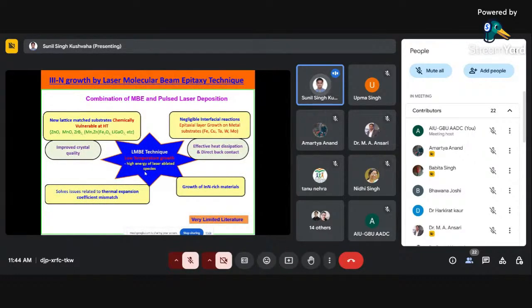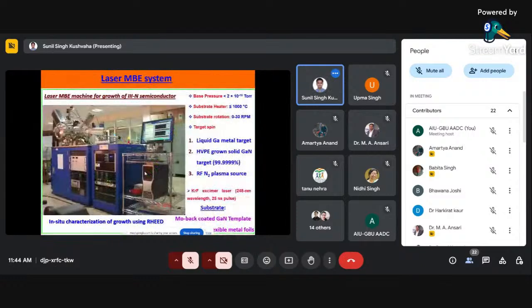So basically, at NPL we have this laser MBE technique, and that is one of the techniques especially used when we are talking about vacuum. This is what we call an ultra high vacuum system. The base pressure is 2 times 10 to the minus 10 torr. So whereas atmospheric pressure is 760 torr, we have 10 to the minus 10 torr. Of course we have control over the different pumps and all other things, because we don't want any contamination or impurity of oxygen or anything inside the system when we are growing gallium nitride. That's the reason we need an ultra high vacuum environment.